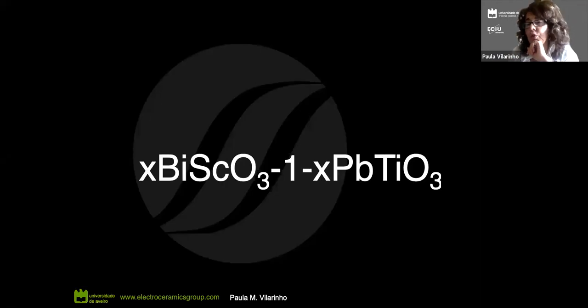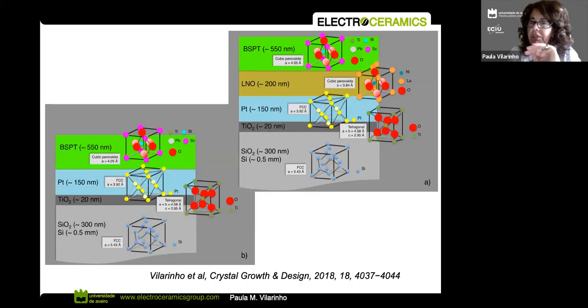Okay, I'm going to show you another example following this logic, using these materials that are indeed enablers. They are piezoelectric, they are ferroelectric, they can be used in all of these sensors. And the example is in continuation of what we mentioned here. So this is our material, a bismuth scandium lead titanate, and it has this structure. And usually these films, to be used in microelectronics, to be used in circuits, have to be deposited on platinized silicon substrates. And usually when we deposit a very thin layer, up to 500 nanometers, this doesn't like the substrate.